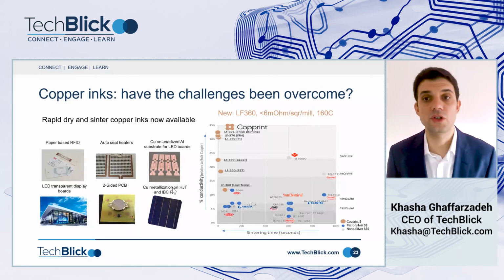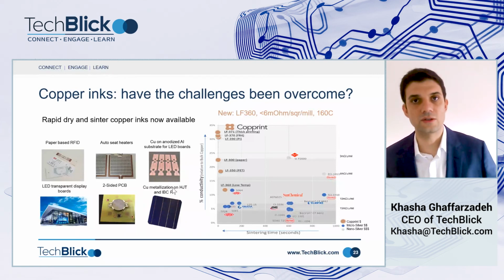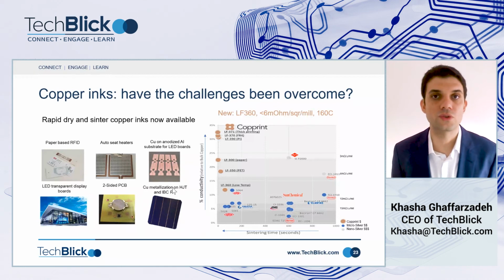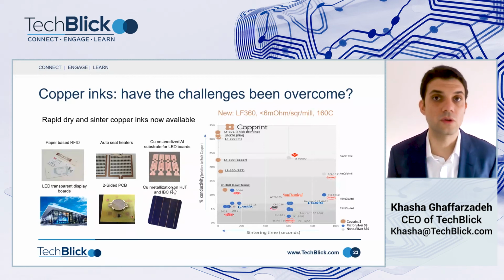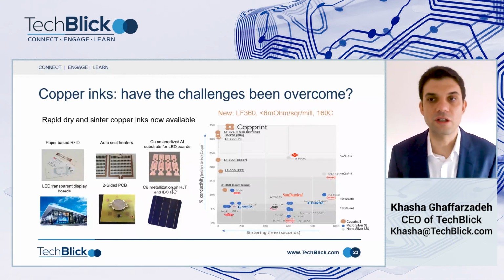And their latest material is actually compatible with, typically the sintering process is, let's say, 200 degrees Celsius, but they also have a process which allows one to sinter at 160 degrees Celsius or so, so compatible with, let's say, potentially heat stabilized PET, and achieve 6 milliohms per square per mil.